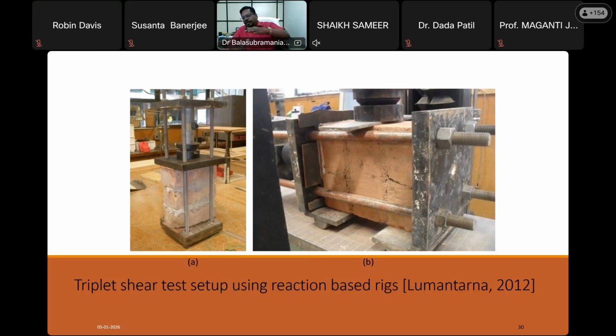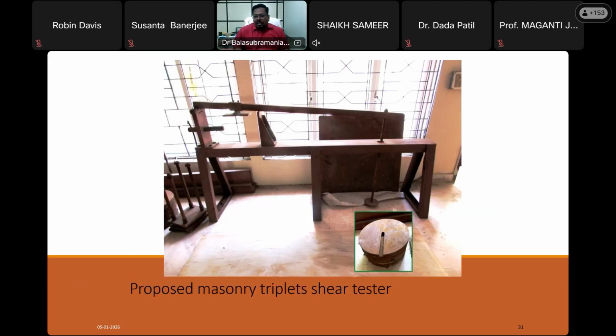Means that when we are applying the lateral load, the specimen will expand laterally, but it is restrained already, so there will be a significant increase in the pre-compression. So to get a constant level of pre-compression, we need to control the load either using the first case, as I showed, servo control actuator, or we can use simple gravity for the load, because if the load is applied by gravity, the dilatation will be allowed. If the specimen dilates, its volume will increase, and the weights will go to the new position. And unlike the case of restraint, if we are applying pre-compression by weight, the weight is going to be the same throughout the time duration of the lateral loading. Okay.